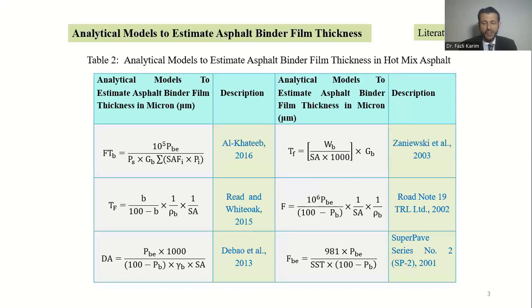And to date, the estimation of asphalt binder film thickness is based on these analytical models. And these models, as per studied literature, are based on various assumptions like spherical shape aggregate, uniform binder film thickness around the aggregate in asphalt mixture, and no clarification on porosity and magnitude of compaction in asphalt mixture. So the inaccurate measurement of asphalt binder film thickness and the consequences of not having an adequate film thickness model has substantially introduced discrepancies in predicting actual performance of asphalt mixture. The basic concept is that the values of film thickness have been assessed, but the models are based on assumptions.